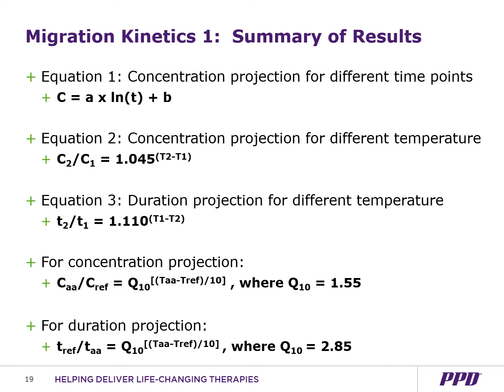And we were then able to equate equations 2 and 3 into the ASTM model and calculate an experimental model Q10 value as shown at the bottom of the slide. For the concentration projection, we had an experimental Q10 of 1.55. And for the duration projection, we had an experimental Q10 of 2.85, which is fairly comparable to the conventional Q10 value of about 2 for first order kinetics, which is a more conservative number.